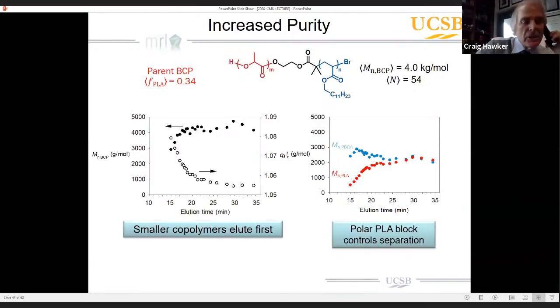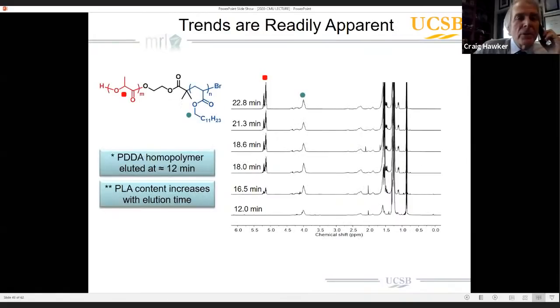And the other nice feature is that we start with a material with a polydispersity of just a little bit above 1.1. And each one of the eluted samples has very low dispersity, anywhere from 1.05 to about 1.08. So we're not only purifying these materials, we're also fractionating them and giving us a library of materials that we can start to look at.